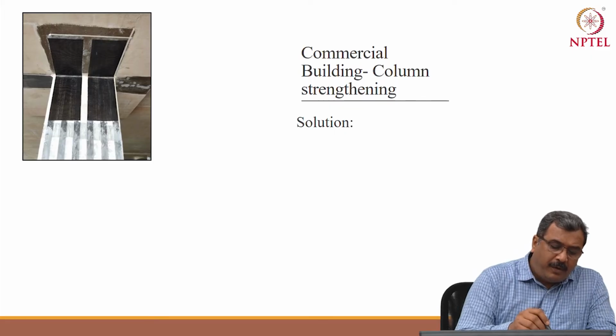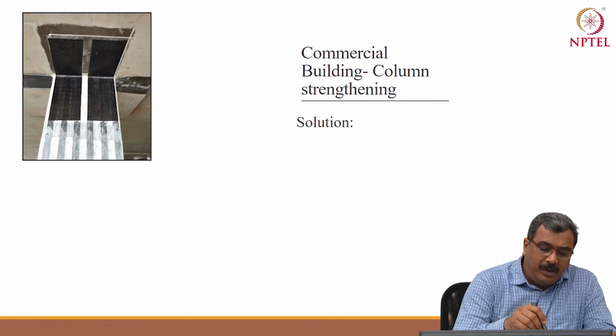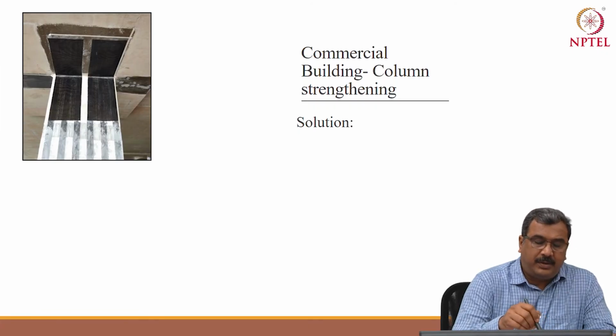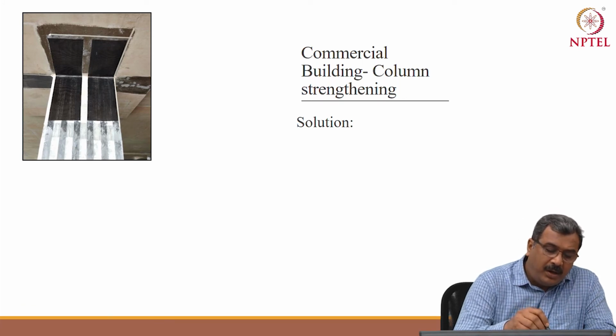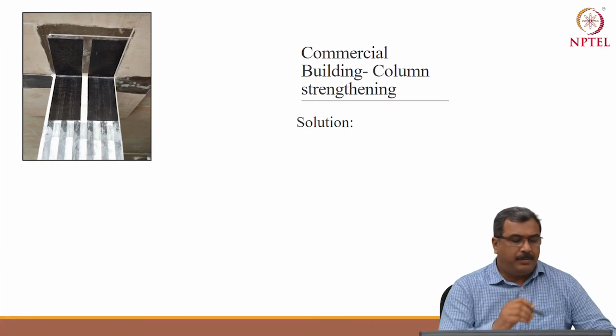Whatever amount of carbon is provided on one face of the column by means of laminate, say 140 into 6, that much amount of carbon has to be provided for junction development in the form of an L shape.